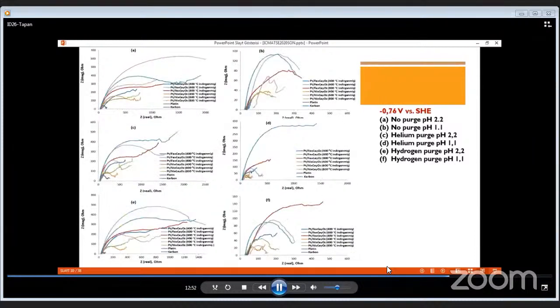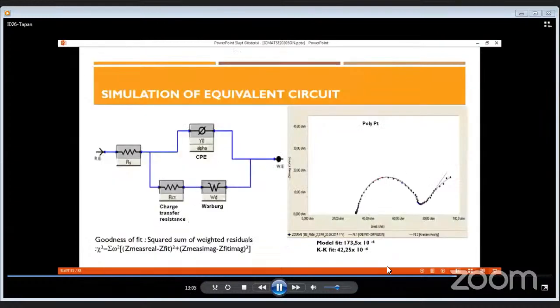This slide shows that at high negative potentials and lower pH values, arc radius also grows. Linear regions were observed outside the impedance arc, which also indicate diffusion resistance. In this slide, the equivalent circuit is shown, which was used to determine kinetic parameters for the electrocatalyst. In this equivalent circuit, RS is solution resistance, followed by a constant phase element, charge transfer resistance, and Warburg diffusion.